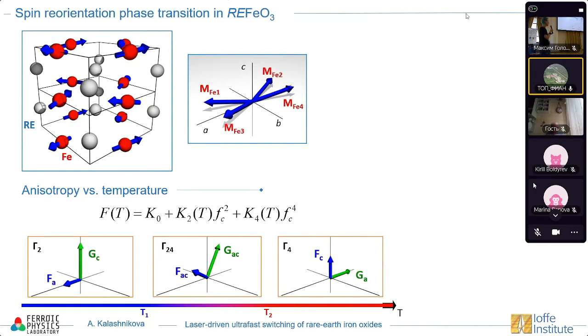However, at a certain temperature, which is dependent on the type of the rare earth ion which we have here, a spin orientation transition happens. And actually, the magnetic moments rotate, and we go to this gamma 2-4 phase with magnetization pointing between the C and A crystallographic axis. If we cool down the material further, a second spin orientation transition happens, and now we have the gamma 2 phase with magnetization pointing along the A axis.